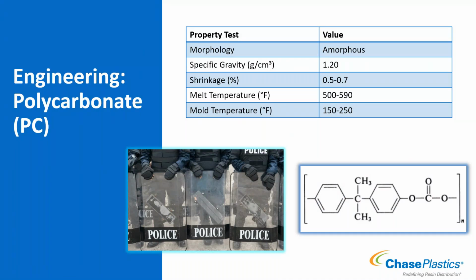You'll see the specific gravity of this material jumps quite a bit. We had been in the 1 to less than 1 range, and polycarbonate jumps up to 1.2. Shrinkage is still in that low range, 0.5 to 0.7, for polycarbonate, amorphous material again. Now our temperatures are starting to creep up, we're in the 500 to almost 600 degrees, a little bit hotter, a little bit warmer temperatures for it. Mold temperatures are in the 150 to 250 range.